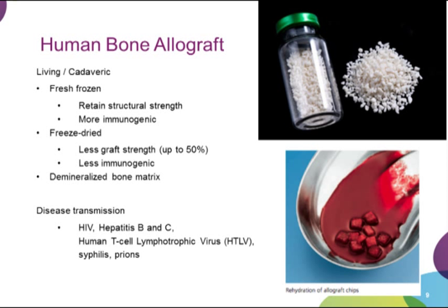When it's initially harvested, it's kept in quarantine for the first 6 months, whilst all of the disease transmission paperwork is done, and that involves both the consent process as well as testing the sample at 0 and 6 months to make sure that it is definitely clear of all these factors. All the bone undergoes gamma irradiation, and then freezing at -80 degrees, and then it can be used, as I said, for up to 5 years afterwards.